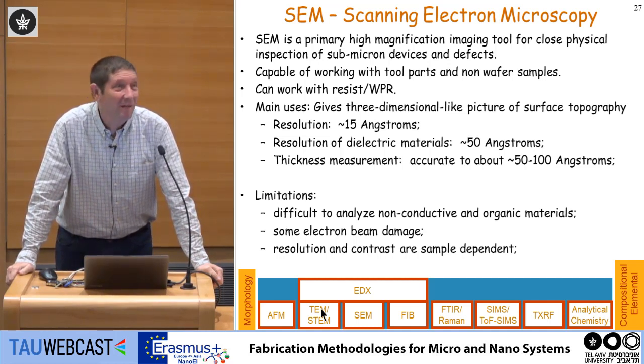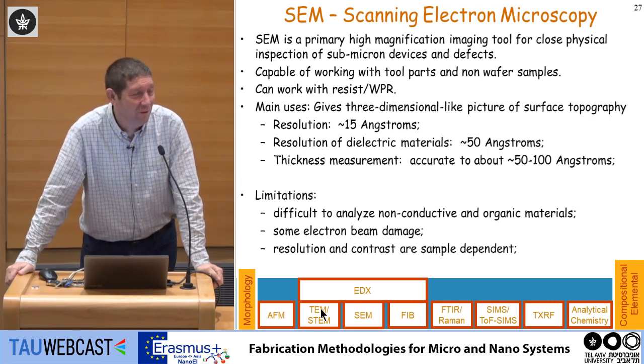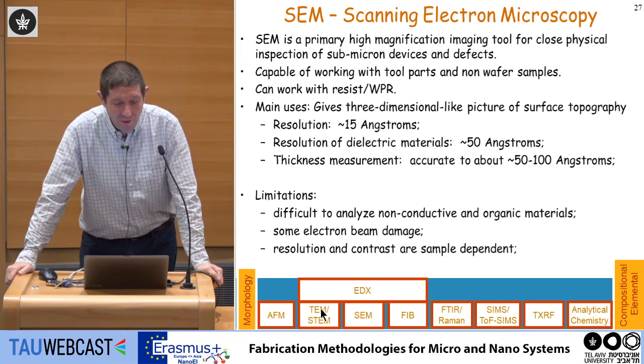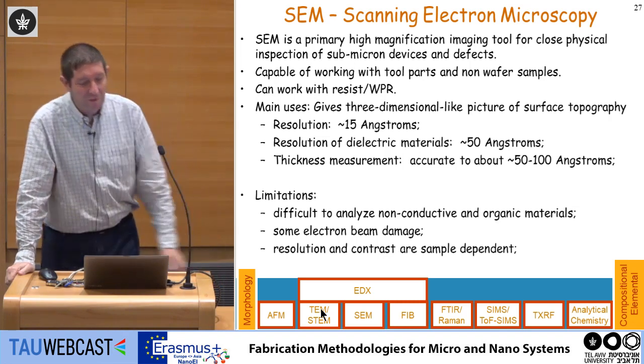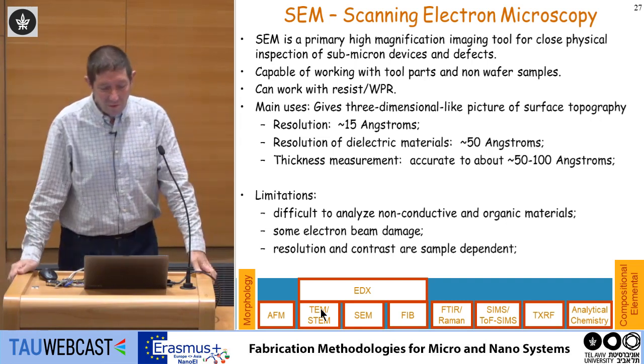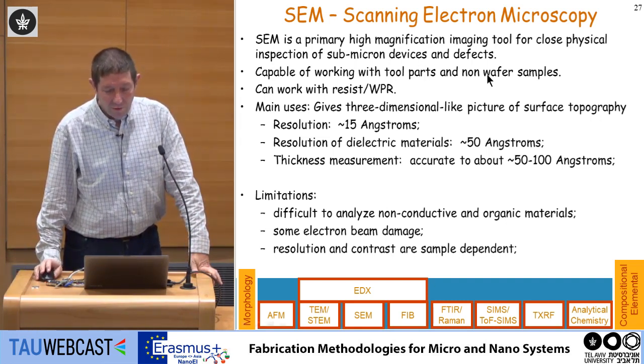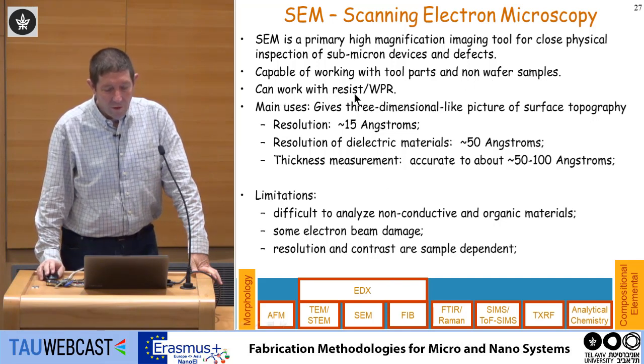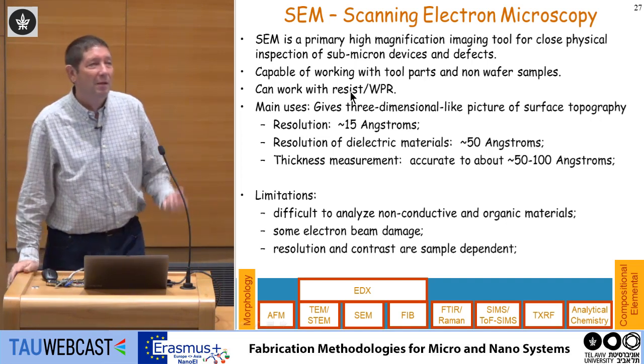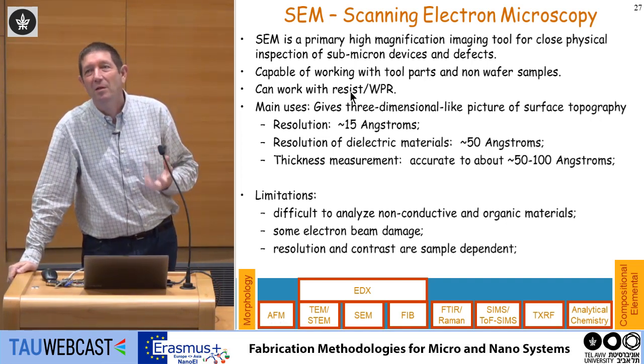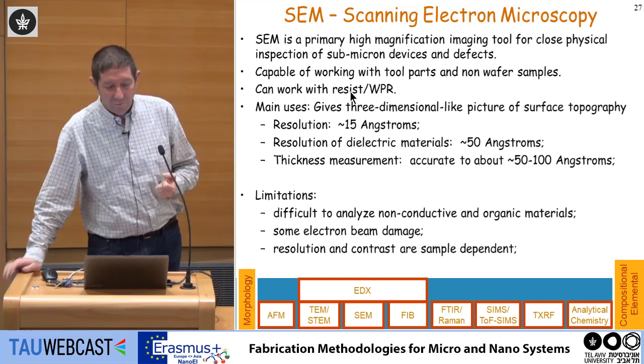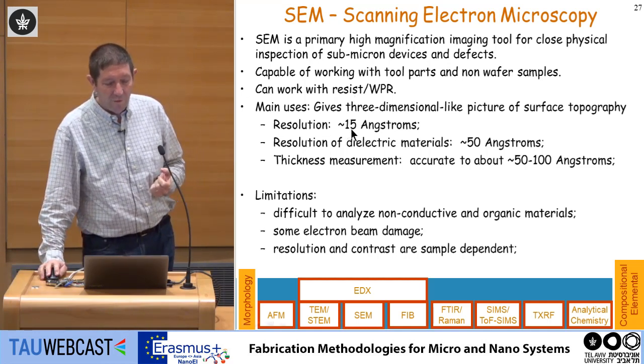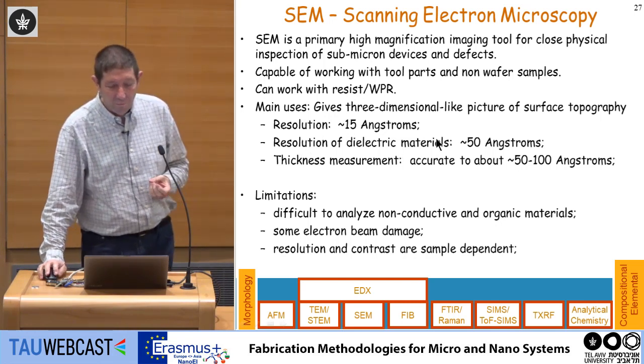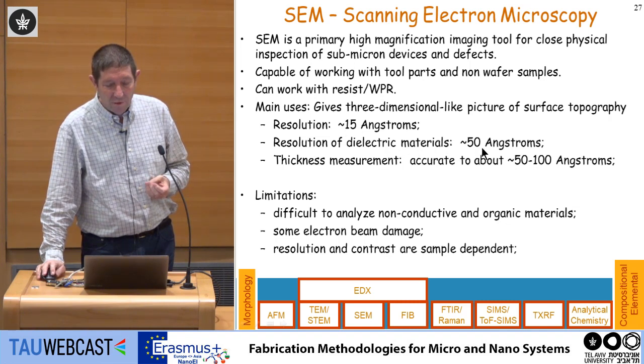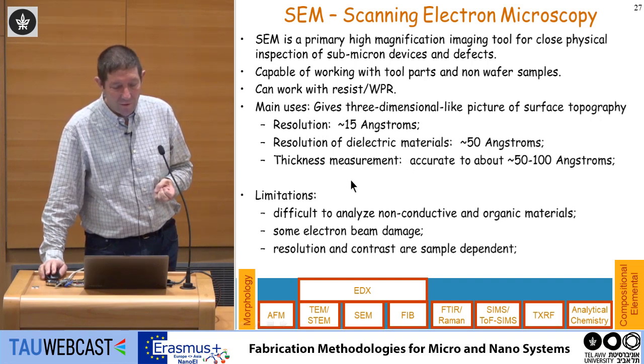scanning electron microscopy, which I assume many of you used or are going to use or are using now. SEM is a primary high magnification imaging tool for close physical inspection. This is like the workhorse of the industry, capable of working with tool parts and non-wafer samples, can work with resist and wafer level. In this system, we are using electrons and their interaction with the surface. It can get very high resolution, about 15 angstrom, like 1.5 nanometer. Resolution of the dielectric materials is a little less. It's about 50 angstrom. And we can also do some thickness measurement with this method.